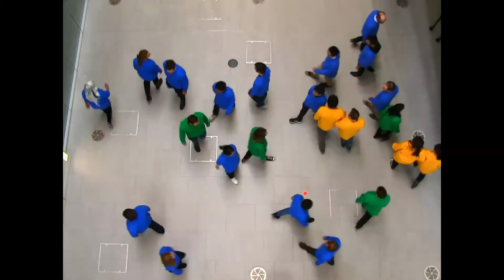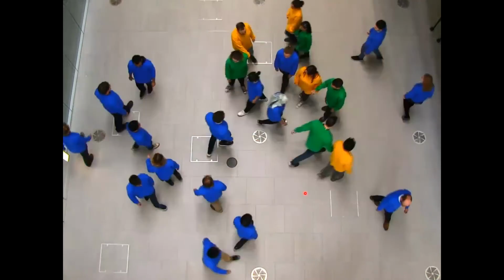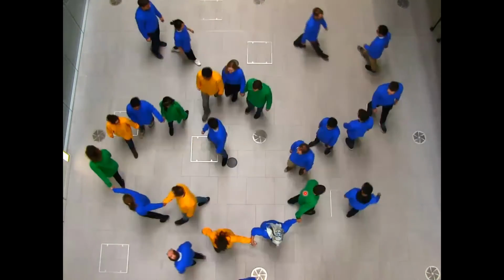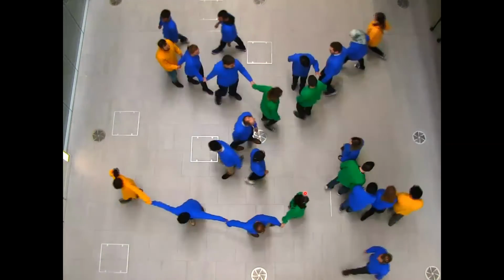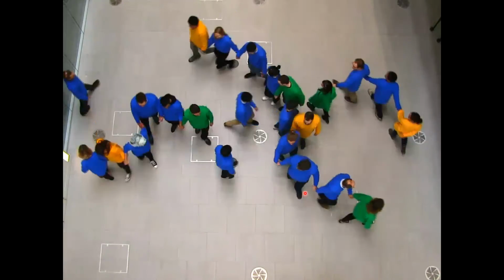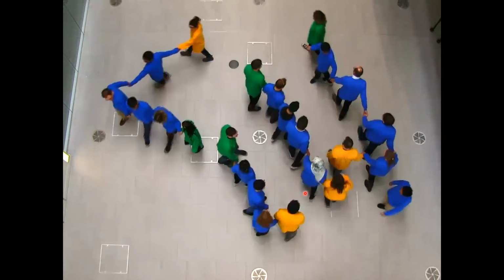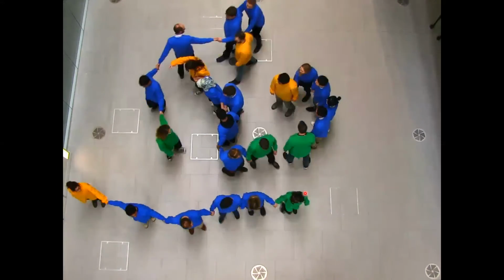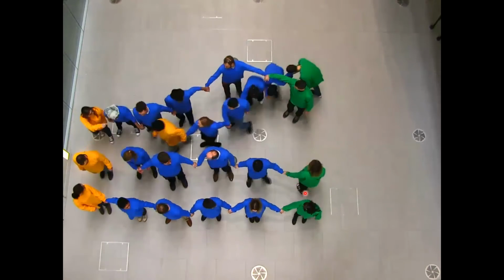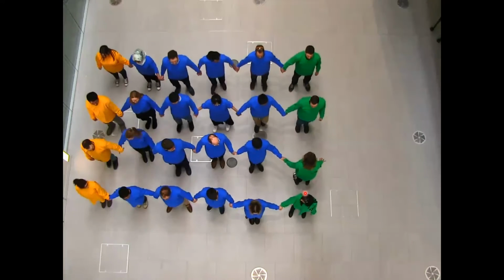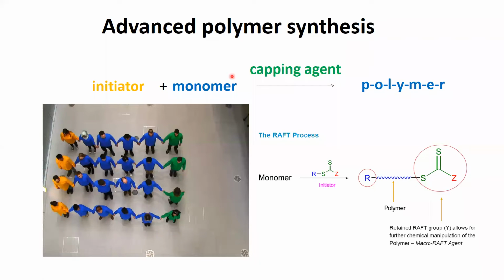So again, the initiator opens, but instantly a green capping agent adds to it, and then we are adding monomers in a very controlled way. And then we make 4 chains, but all of the same length, and they all have our initiator at one end and our capping agent at the other. And this allows us to add in a second monomer and make blocks and make things much more complex.